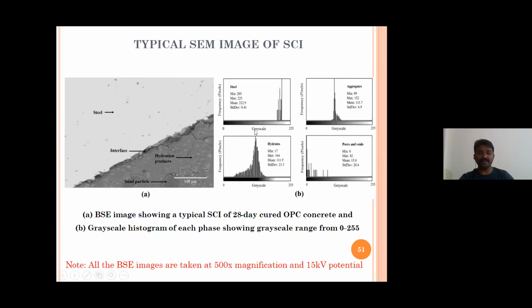Steel's gray value is nearly around 255. That is why the steel appears brighter in the SEM images. Aggregates are somewhere between 0 and 255, so they appear a little grayish compared to this. Hydration products vary from very close to 0 up to about 150 grayscale. One important factor you need to observe here is pores and voids. Pores and voids are almost closer to 0.